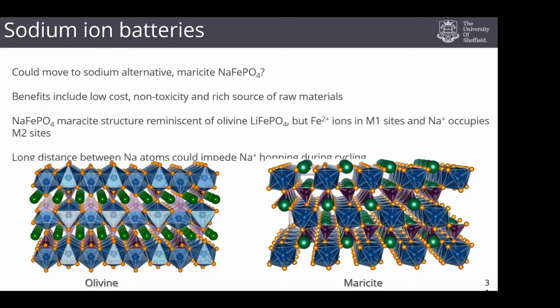So now you start to see that the lithium ions are blocking the lithium channels. Sorry, sodium is still here in these channels, and the phosphates are also in the channel. They're blocking the movement of these sodium ions, and that long distance between sodium is impeding the hopping that needs to happen. For these materials to be ionically conducting, the ions need a spot to jump into, and something needs to get out of the way so they can get into that spot. In this case, that's very, very difficult.